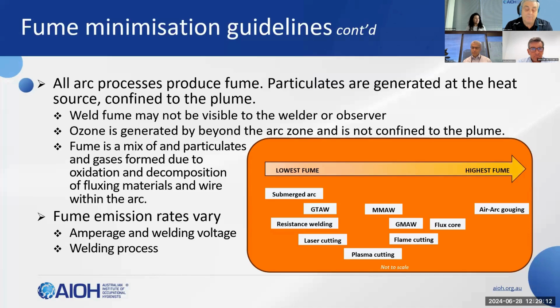Actual composition and hazards associated with each consumable can be found by referring to the safety data sheet supplied by the consumable manufacturer. For those unfamiliar with ozone, it is formed by the action of the ultraviolet radiation from the arc on atmospheric oxygen, and where there is a lot of surface UV reflection, ozone can be found accumulating away from the arc. That is particularly the case for stainless steels and even worse for aluminium. It should be noted, though, that consumable and other power source manufacturers are doing a lot of research to minimize fume generation rates through what's called waveform controls applied to the gas metal arc and flux cored arc process groups. Of particular note, fume generation rates for thermal cutting can also be very high, and unless the process operator can keep their head out of the plume, the fume generated is potentially problematic.